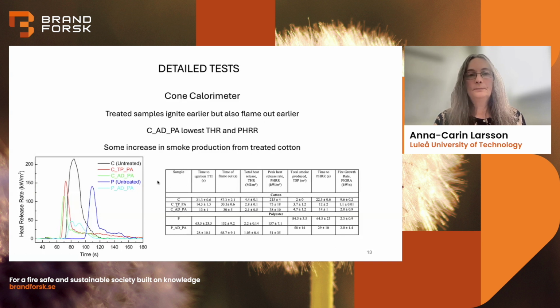If we look at the collected data, we can see the samples ignite earlier, but they also flame out earlier. So the burning time is shorter for the treated samples because they self-extinguish. So less heat is released, and the peak heat release rate is also lower. There's some smoke production on the cotton, but reduced in polyester. The FIGRA index is shown here as well.